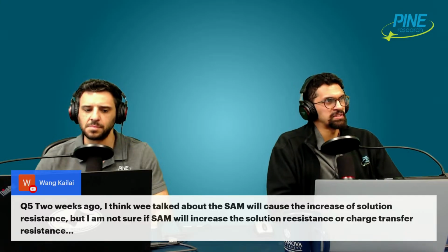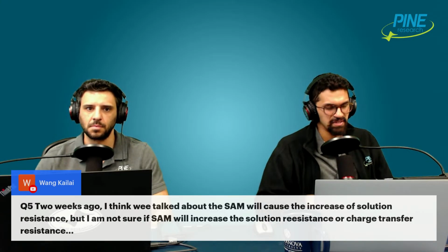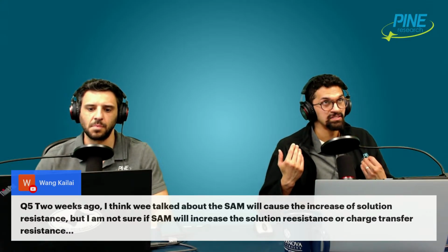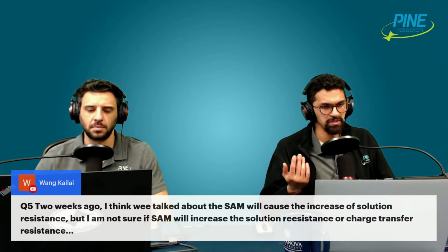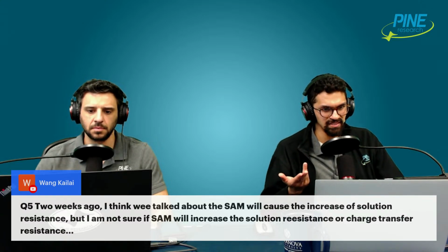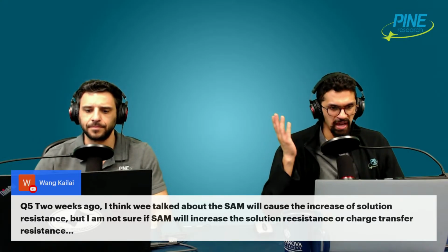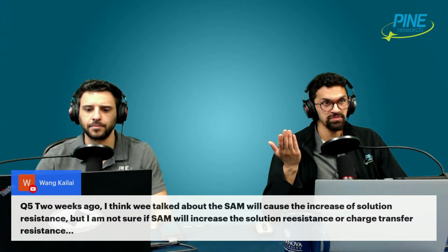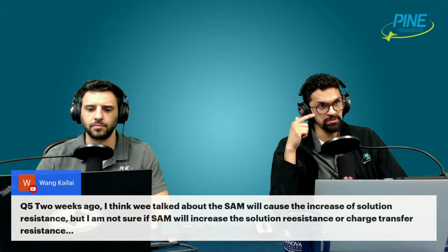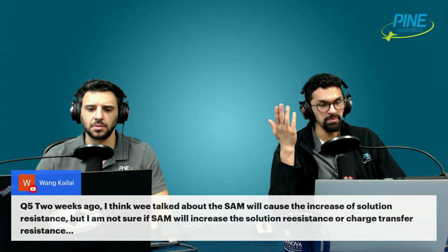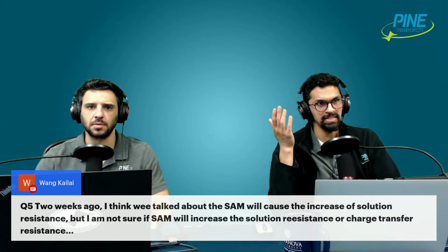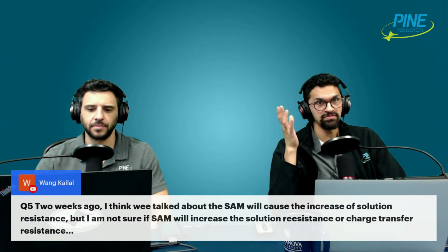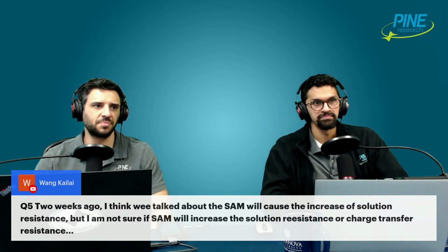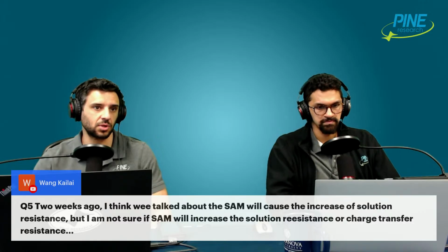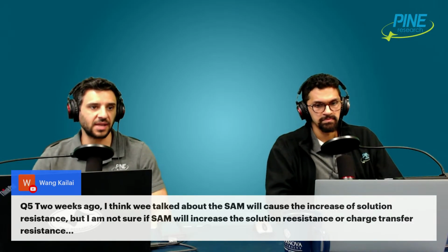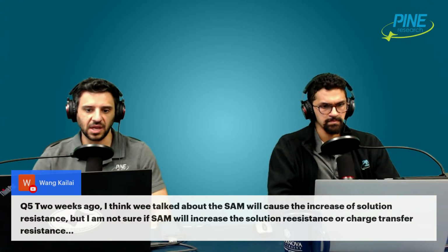When you talk about heterogeneous electron transfer, yes, if the nature of the metal itself played a role, then it would. But we're talking about a self-assembled monolayer. You've blocked sites on, say, your gold. You have a gold thiol self-assembled monolayer. You can still have electron transfer to species. There's always a tunneling mechanism, so this would be homogeneous electron transfer. And homogeneous electron transfer rate kinetics are based on the molecule itself, so that shouldn't be impacted by the monolayer. Now you might have worse current, for example, because of the resistance from the monolayer, but if you could isolate the kinetic contribution from the other stuff, the kinetics would in theory be unchanged, is what you're saying.